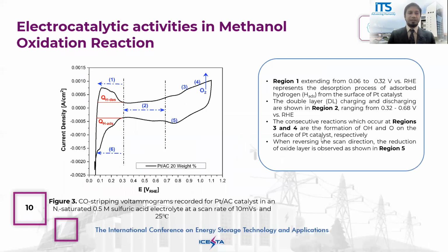And then we also subjected the resulting activated carbon to use as a fuel cell catalyst. We combined it with platinum, and the activated carbon supported platinum was subjected to the fuel cell, particularly electrocatalytic activation in the methanol oxidation reaction. Region 1, extending from 0.06 to 0.32 volt, represents the desorption process of adsorbed hydrogen from the surface of the platinum catalyst. Region 2 is the double layer charging and discharging from 0.32 to 0.68 volt. The consecutive reactions occurring in regions 3 and 4 are the formation of OH and oxygen on the surface of the platinum catalyst. In region 5, the reverse scan region, the reduction of the oxide layer is observed.